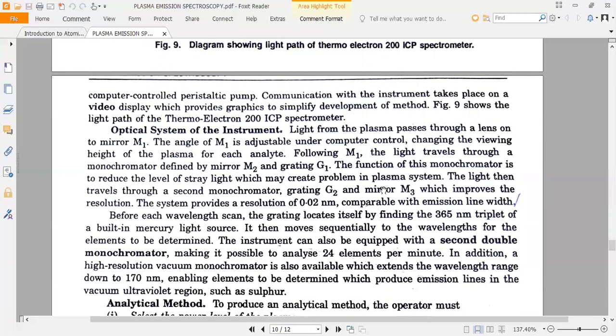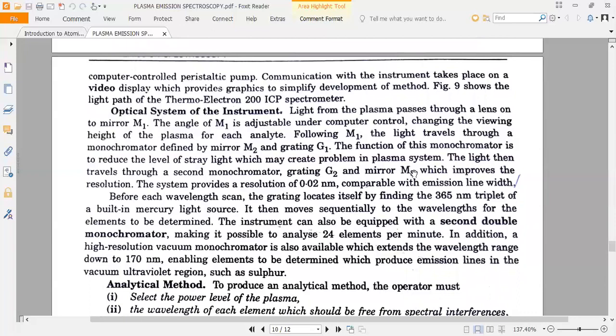The light then travels through a second monochromator, grating G2 and mirror M3, which improves the resolution. The system provides a resolution of 0.02 nanometers, comparable with the emission line width. Before each wavelength scan, the grating locates itself by finding the 365 nanometer triplet of a built-in mercury light source. It then moves sequentially to the wavelengths for the elements to be determined.